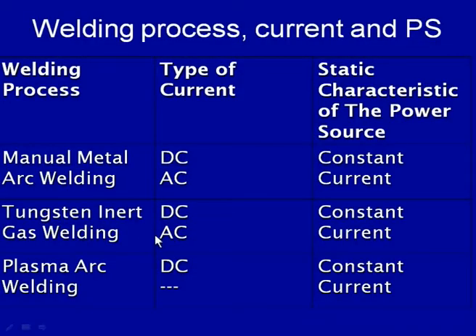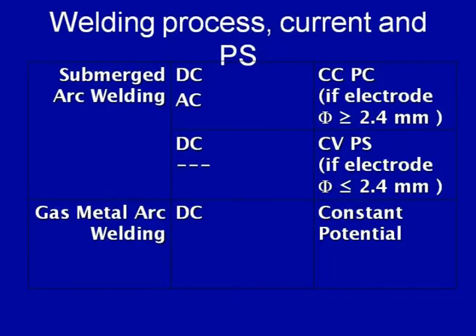The tungsten inert gas welding with the AC is used when welding aluminum and magnesium kind of metals for obtaining the benefit of the cleaning action, but the DC EN is normally used with the tungsten inert gas welding process, so that the longer life can be obtained and more heat can be generated in the workpiece side. Similarly, the plasma arc welding DC is normally used with the constant current static characteristic power source, so that the fluctuation in arc length benefit can be obtained.